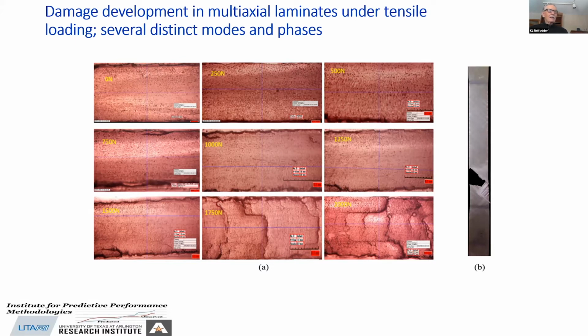As we go to the bottom right, we can see that some of these matrix cracks do indeed find each other. And by the time we get to the bottom right, there is indeed a path, a clear defect path through the thickness of these materials. And we might expect that that is the final phase just before failure. And indeed, in some cases it is, but in other important cases, there is another feature not represented here yet. Nevertheless, we can see the failure diagram of the specimen on the right.